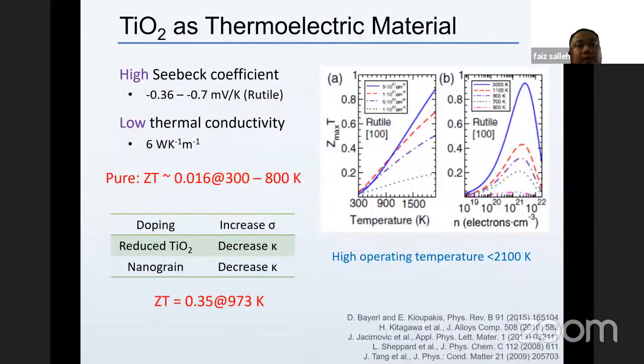So if we look at the thermoelectric properties of TiO2, this is a theoretical report regarding the rutile phase TiO2. It is reported that the rutile phase has a higher dimensionless figure of merit compared to the other polymorphs, for example brookite and anatase. And we can also see from this figure that the ZT of TiO2 depends much on the temperature, and TiO2 can operate up to quite a high temperature, 2100 Kelvin. So it's good for many kinds of application. And it also strongly depends on the carrier concentration.